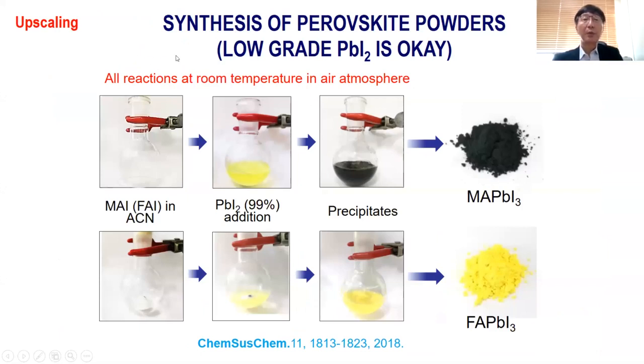And for upscaling, the material may be an issue. Recently, people are using high quality, very expensive PbI2 to get high efficiency perovskite solar cells. However, that is not suitable for commercialization. So you would like to use very low grade PbI2. Using this low grade PbI2, we made high quality perovskite powder. For instance, this is at room temperature.